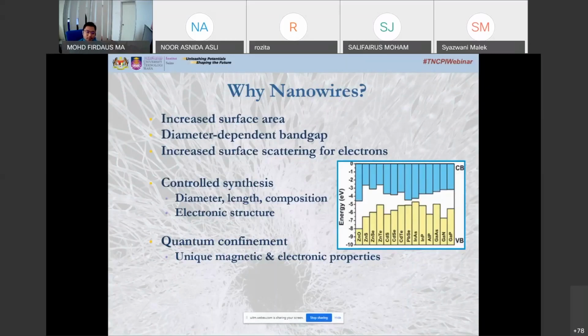So why nanowires? The first one is the increase in surface area, and the diameter-dependent bandgap, and increased surface scattering for electrons. And then it can be controlled; it is a controlled synthesis. As I mentioned to you before, we can control the length and the diameter that we want through parameters like the concentration, the deposition time, and so on. And also quantum confinement, which contributes to unique magnetic and electronic properties. This quantum confinement effect also describes the electronics in terms of energy level, potential well, valence band, and also the conduction band. The confinement effect can be observed when the size of the particle is too small, which refers to the nanowires, comparable to the wavelength of the electron.